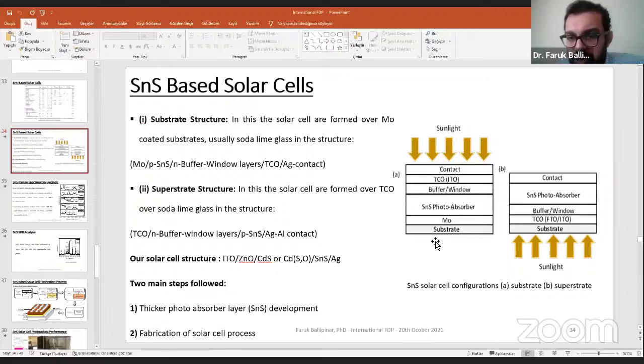So looking at this structure, this configuration, the substrate and superstrate. In figure A, there is a moly-based contact, and in this one we have only just silver contact on the top of them. We just use the transparent conductive oxide layer. On the top of the moly-based substrate, the tin sulfide needs to be developed. During sulfurization, it might be a problem to form moly disulfide, because people use the moly-based substrate on the bottom.